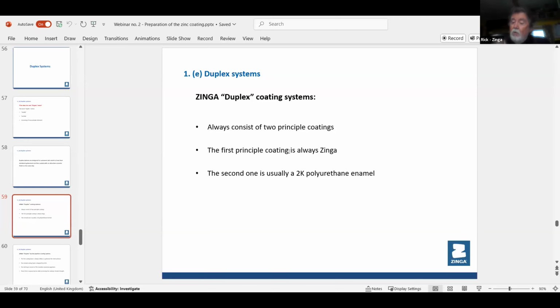If you apply the second coat, also nice and light, it'll sit up and dry with a high gloss. You get a perfect finish. When you put the first coat and it's all matte, if there's a couple of shiny bits, give it another 10 minutes. That's all. Then come back, it'll be matte. Then apply your second light coating, because most polyurethanes go on at 60 to 80 microns anyway. So your second light coat, it'll always sit up nice and give you a nice shiny finish, and that's it. The job's done. So that's basically your duplex.